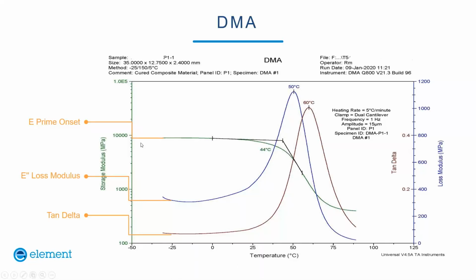The storage modulus or elastic modulus is E prime, and it's this first green curve. You can see that it's fairly steady, and then it really dips down. And that's an indication of where the loss of mechanical properties occurs. And then by drawing tangent lines on these curves, we can determine an inflection point, or what we'll call the glass transition from E prime onset of 44 degrees C. You would just go down here to the 44. This is usually the lowest temperature you see on a DMA, and it's most conservative. And as I said, it coincides with the degradation of mechanical properties.